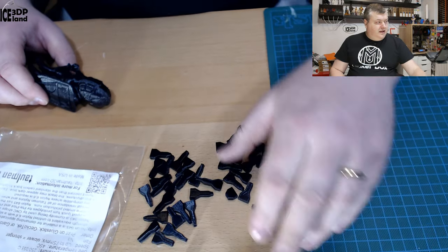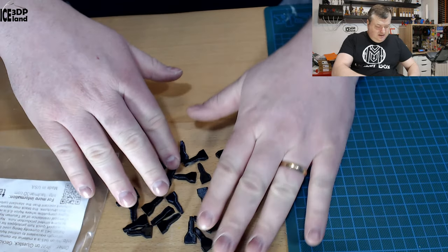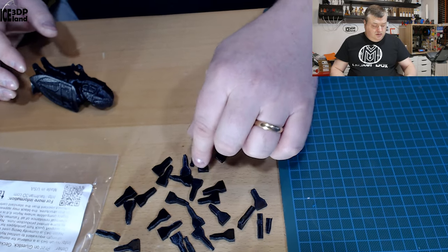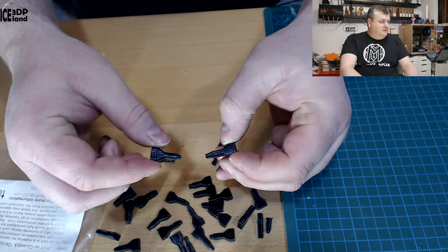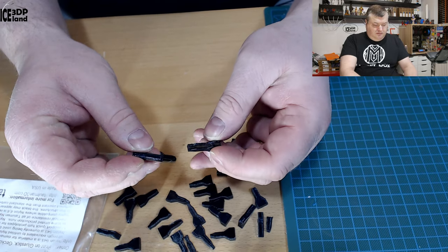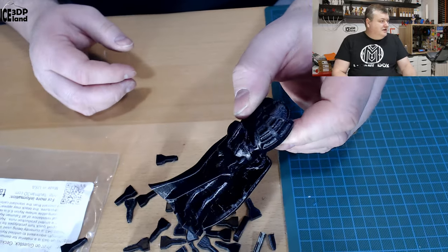For this filament I want to do a break test on it. I don't have many samples of nylon filaments — I spent almost all of the filament on those break tests. Compared to other nylons, on average it performed a little bit better, maybe 10% better, in this break test where I pull these things apart in my break test apparatus. I have several videos on the channel on that procedure. Basically it's a machine that measures the force needed to pull this apart, so it tests for layer adhesion. A lot of filament went into this, but I've printed a series a lot.